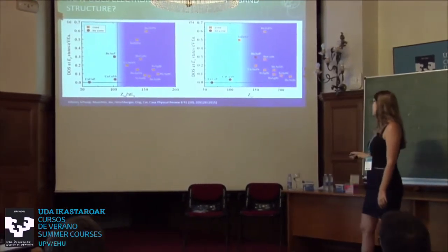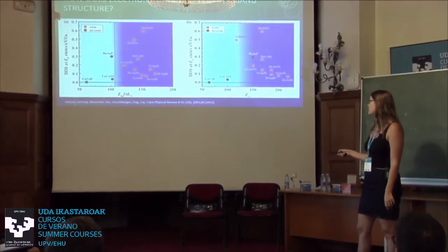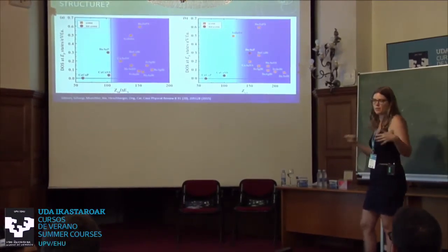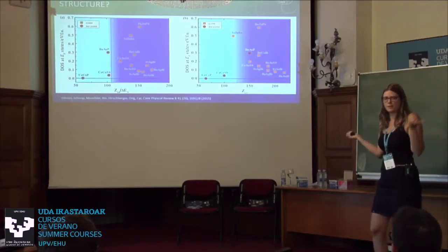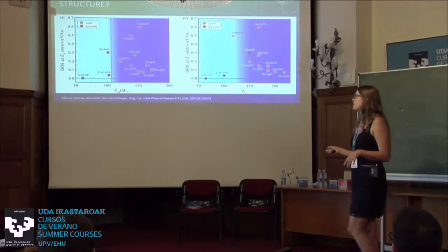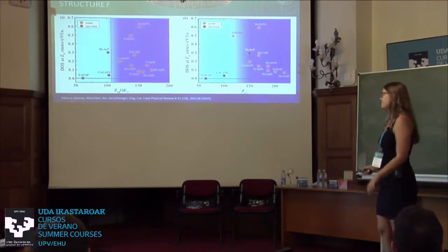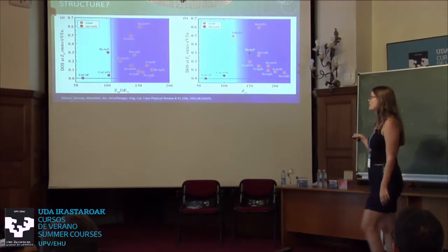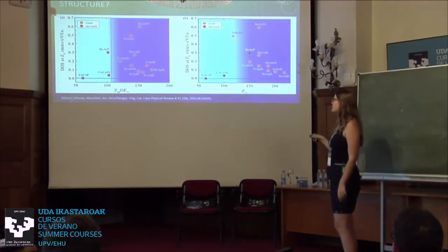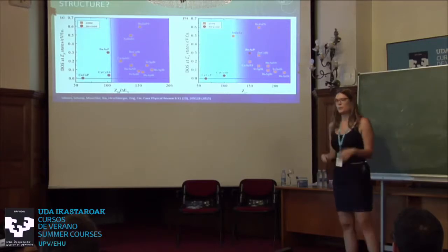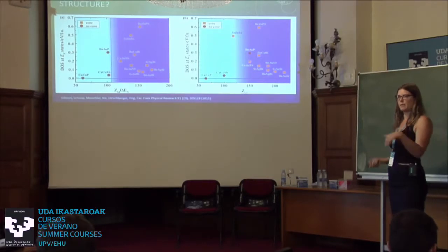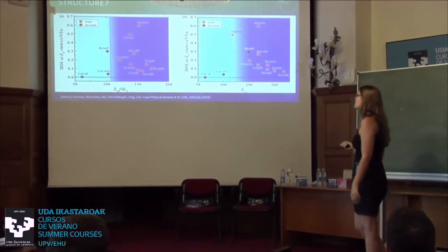And then we made two different plots versus the x-axis. On one plot here, we plot the total nuclear charge, which is somehow a measure for the amount of spin-orbit coupling because it increases with Z, divided by the electronegativity difference of the elements. And then here in this plot, you see, so the red points, they don't even have a Dirac crossing, and the orange points, the Dirac crossing is there. And so there's a clear phase transition, basically, of when you can have that and when you don't have a free Dirac semimetal. So is there a band inversion or not, based on spin-orbit coupling and electronegativity difference.